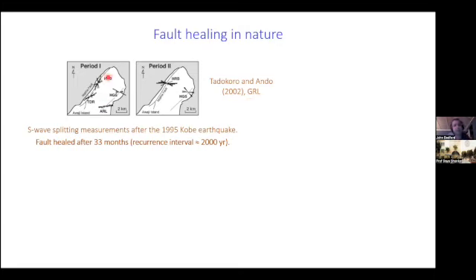shear wave splitting measurements around the Nojima fault in Japan, which hosted the 1995 Kobe earthquake, and they found that all the damage that had opened up during the earthquake had pretty much healed within 2 to 3 years after the main earthquake event, which is very quick considering the recurrence interval on this fault of large earthquakes is predicted to be around 2,000 years.